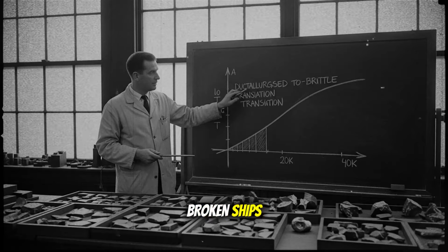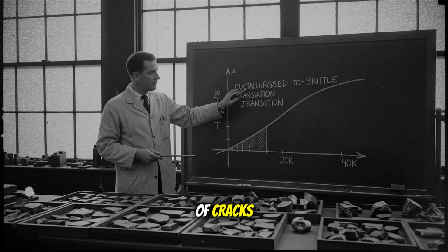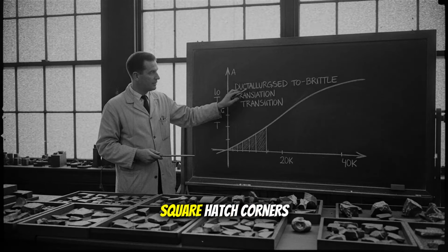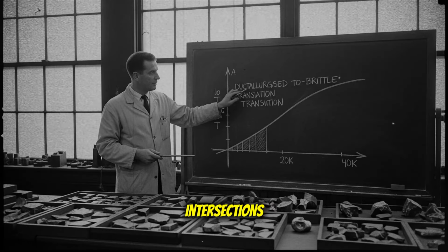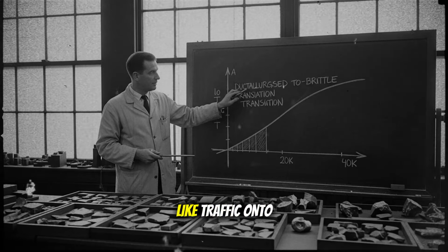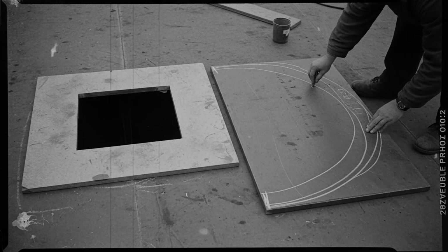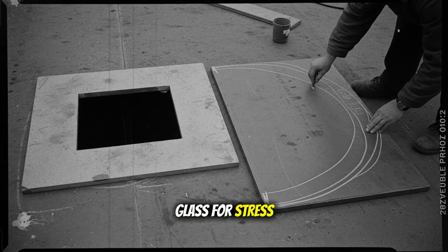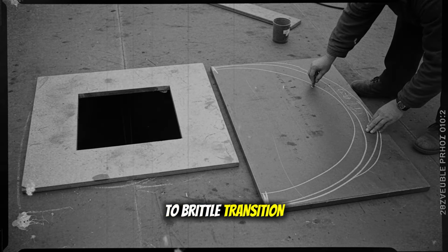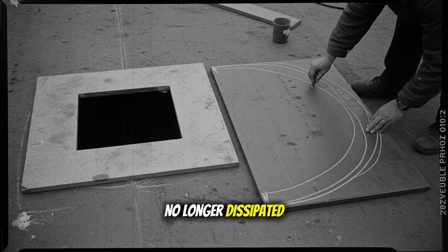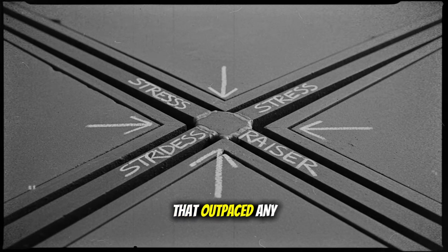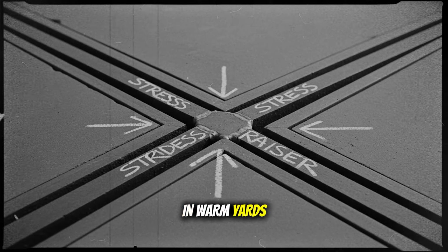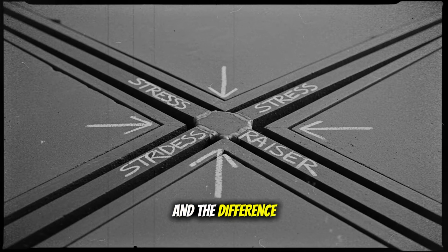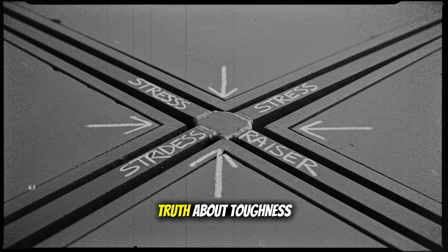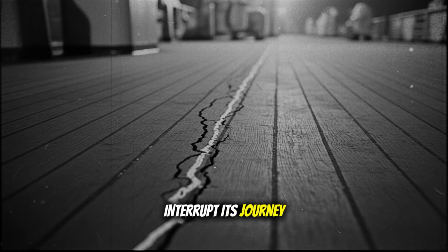Investigators crawled through broken ships with mirrors and chalk, tracing the birthplaces of cracks and finding them again and again at stress raisers, square hatch corners, abrupt cutouts, welded intersections, places where the steel's internal loads piled up like traffic onto a narrow bridge with no shoulders. Each corner acted like a magnifying glass for stress, and when winter chilled the plates toward the ductile to brittle transition, those amplified stresses no longer dissipated through yielding but snapped suddenly into a running fracture that outpaced any human response. In warm yards the metal bent, in cold seas it broke, and the difference was not a moral failing of a worker but a material truth about toughness, temperature, and the way a continuous welded skin leaves a crack with nothing to interrupt its journey.